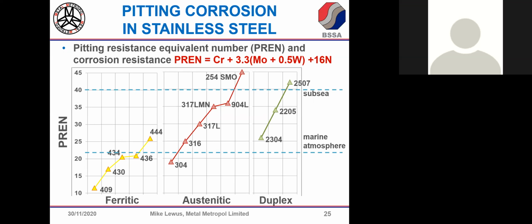But you'll see as we go from something like 316, which is in the middle band of grades there, the red line, as we move up to something like 904L, which is one of the more corrosion resistant grades we pointed out on the marine application slide, we've got a significantly higher pitting resistance, a higher PREN number. And as I say, 904L's termed a super austenitic. We can get more corrosion resistant than that. The second blue line, the one marked at 40, is typically the line you've got to be above for good performance subsea, so if you're below the water line.